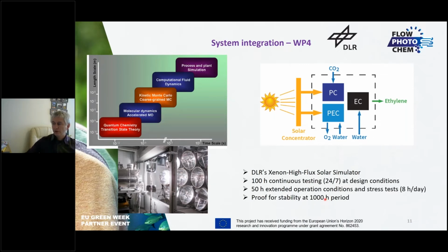So in order to achieve the stability performance that we require over 1,000 hours, we will be conducting two different types of testing at the DLR facilities. We'll be conducting continuous testing of about 100 hours, 24 hours a day, and also stress tests of 8 hours a day, switching on and off, so that we can mimic the stress conditions that you would require for performing stability tests over 1,000 hours.